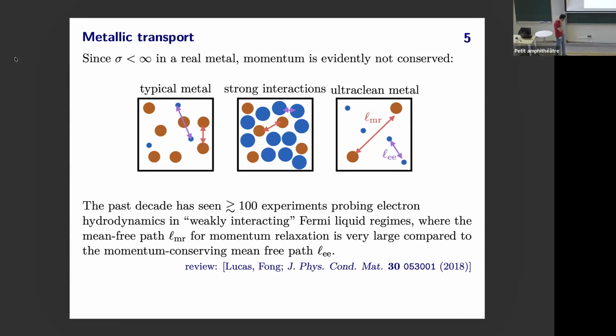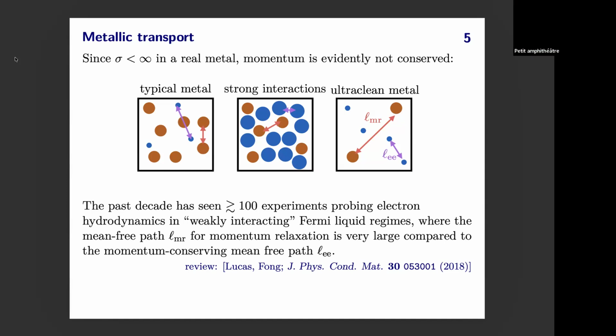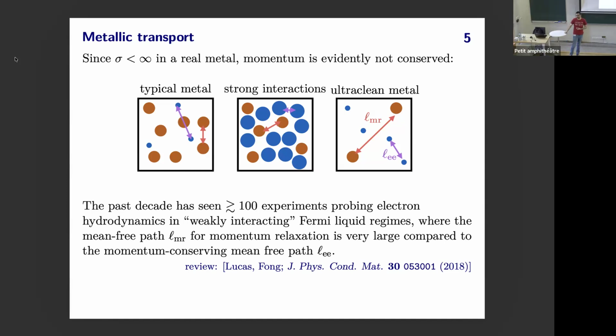Yeah, so the canonical argument here is that you want the Fermi radius, the radius of the Fermi surface, to be 1/4 or less of the Brillouin zone. Then in a two-body collision, you don't have enough crystal momentum to wrap the Brillouin zone. The reason most experiments in this field are on these 2DEG devices like graphene or gallium arsenide is precisely because they have tunable and extremely tiny Fermi surfaces. So in some sense, there's a good reason to expect that this is even possible.